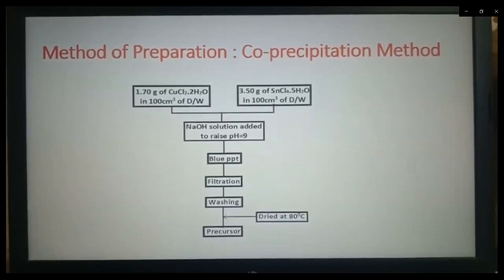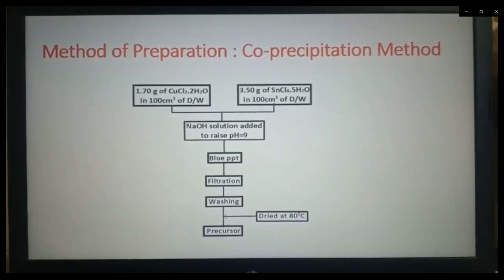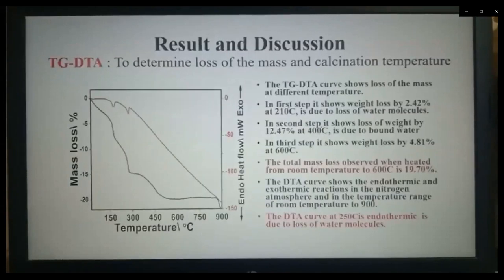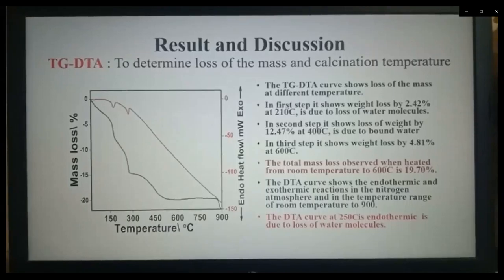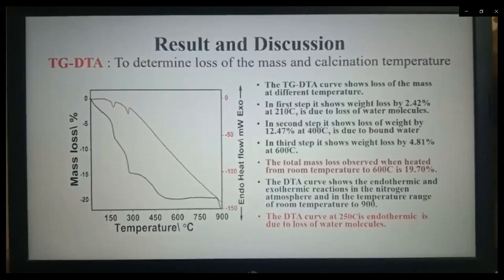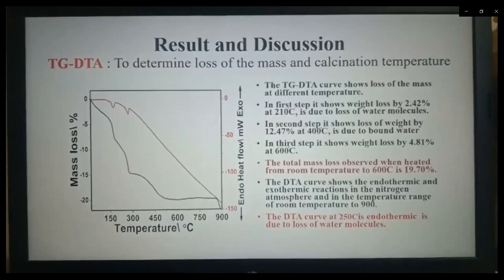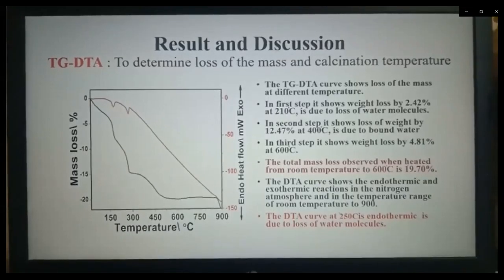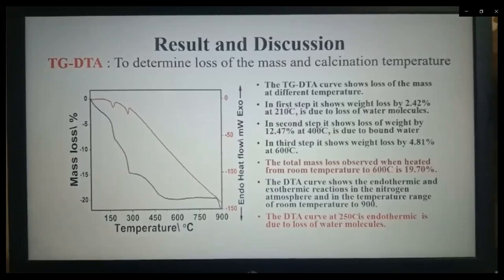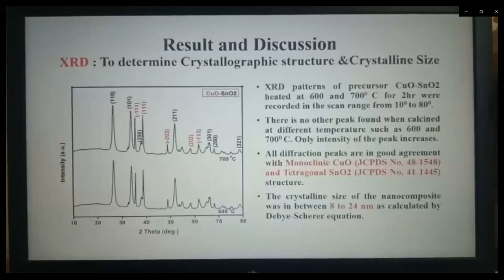So let us start with the method of preparation. Here we use a co-precipitation method. The important thing is pH. We have to maintain pH 9, so we get the precursor. From TG-DTA, TG gives the weight loss, that is 19.70, whereas DTA gives the calcination temperature, that is 600 degrees Celsius.